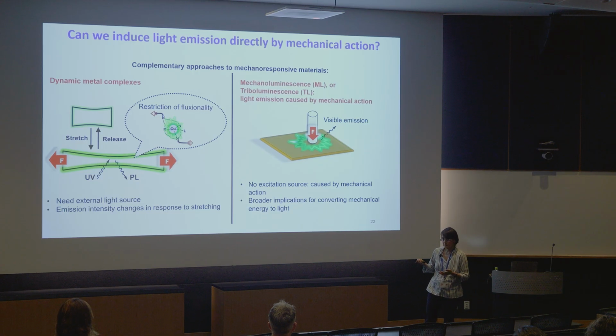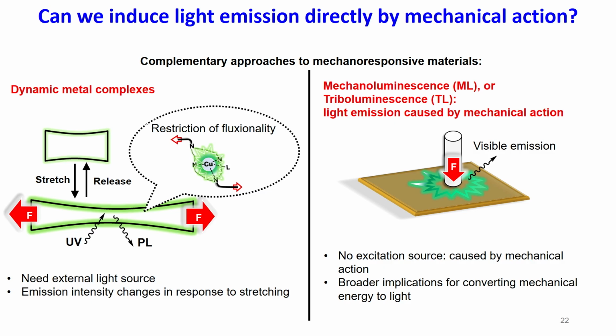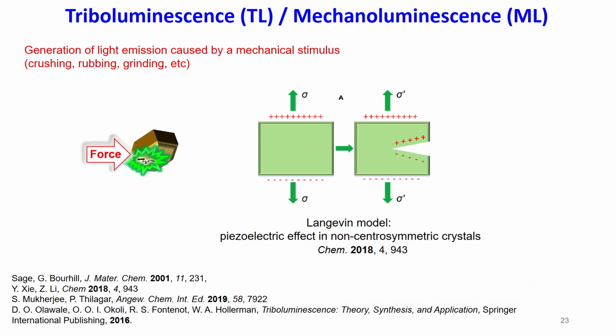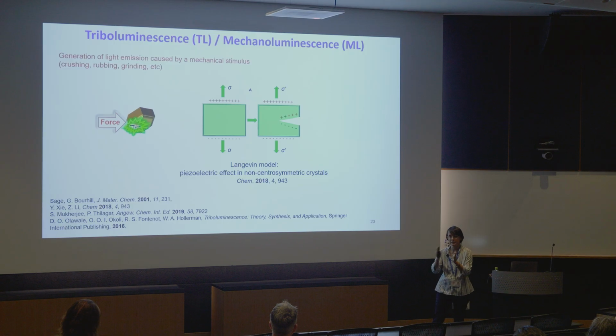And in triboluminescent materials, most studies have been done using crystalline materials. And the dominating theory was that in crystalline materials, when you break the crystal, you fracture it, and at the crack point, you generate in unsymmetrical crystals oppositely charged surfaces. And if the thus generated electric field is strong enough, this may lead to the excitation of the surrounding gas, so essentially the gas discharge. And those lines you saw with the spectrum recorded upon breaking sucrose was actually discharge of the nitrogen gas. So this is one model to explain, and actually there are many exceptions to it as well.